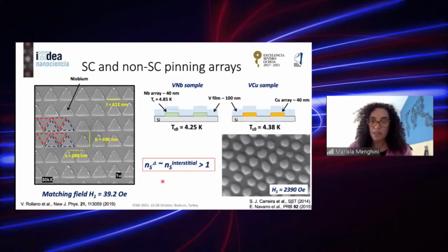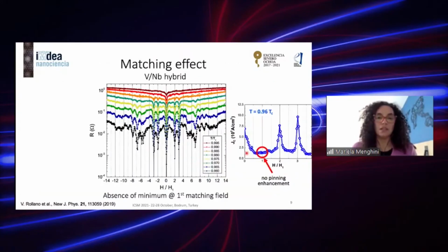the physical triangles. So this is very different from the previous case, where the matching field was much larger, 2000 Oe, and the nanostructure was made by using an alumina layer. So the separation between these dots, so these were also niobium dots on a vanadium film, is much smaller, and the interstitial space is much smaller, and the array is not perfectly periodic.